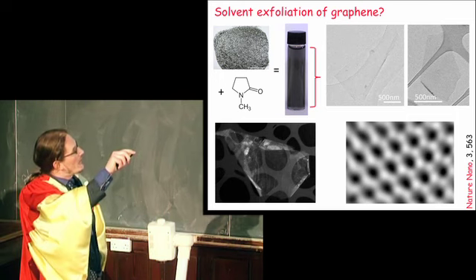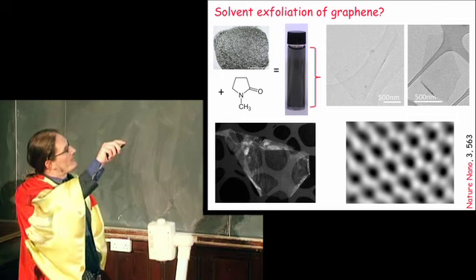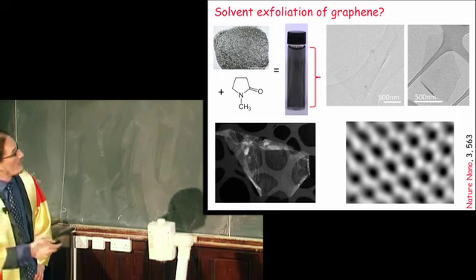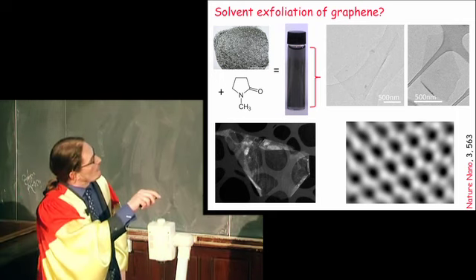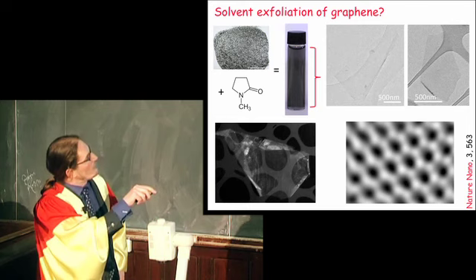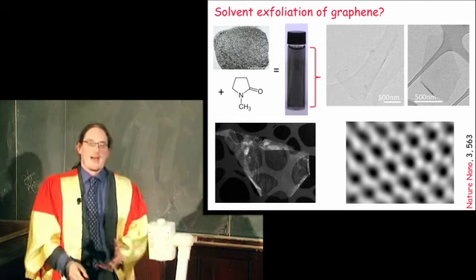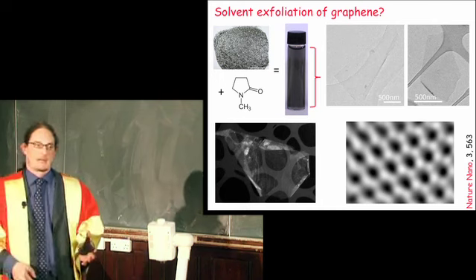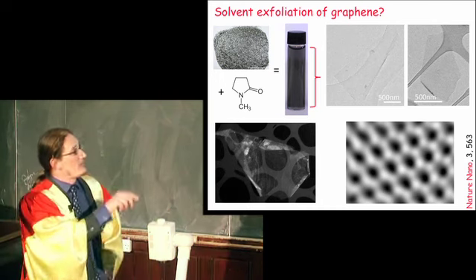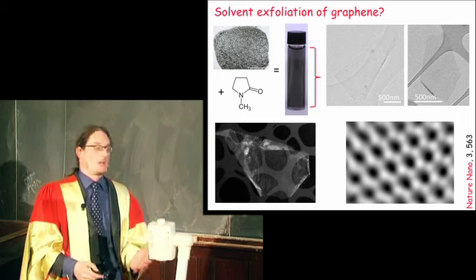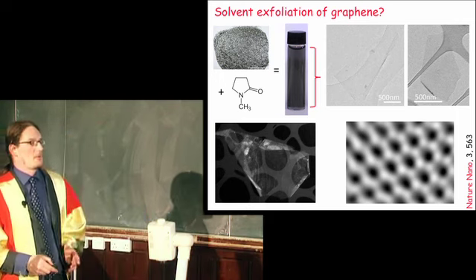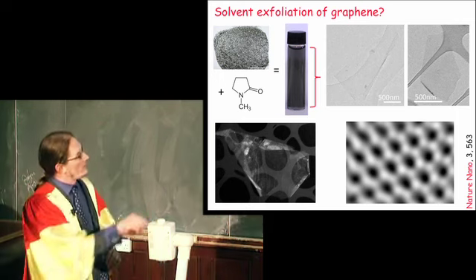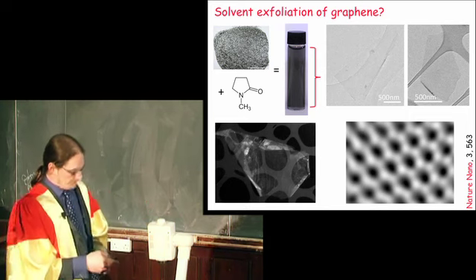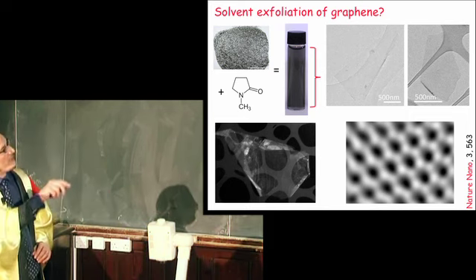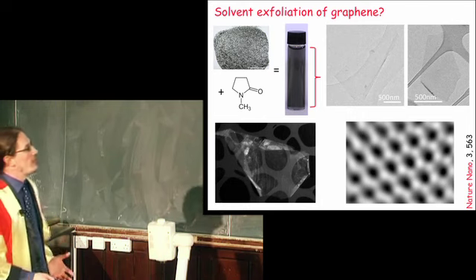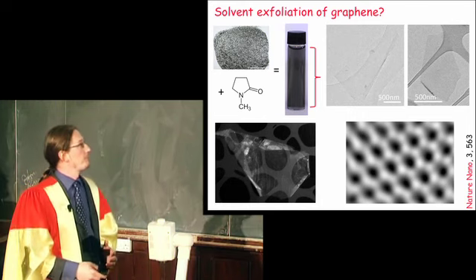So you can look in and take a closer look at these pieces of graphene. If you look with the atomic resolution microscope, you can see individual graphene atoms in a structure that is exactly as expected. Some people I show this to think that this is a simulation or a model. This is not. This is an experimental image. Now, it has been filtered to remove noise, but this is an experimental image. And the graphene, as you can see, is really good quality, and most importantly, it's defect-free.